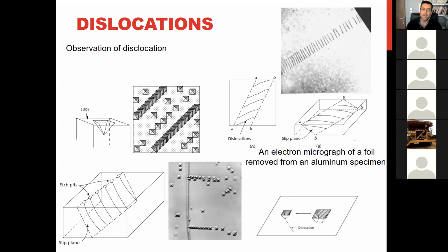You know, to evaluate metallic materials and to see the crystal structure and microstructure of metals, we have different characterization methods. One of them is XRD, or X-ray diffraction. By applying X-rays on a metal and observing the diffraction of these X-ray waves, we can know the crystal structure. That's why we say this is FCC, this is BCC, this is HCP. Another method is that we can cut the metal, polish the surface, and by putting this polished surface in an acid, something corrosive, we can observe some defects.